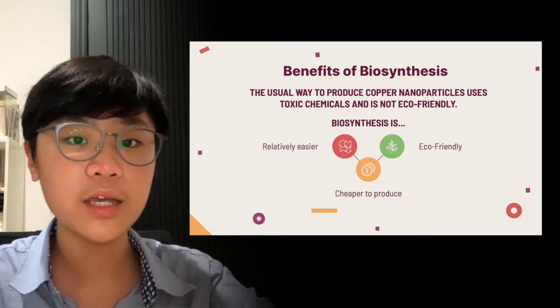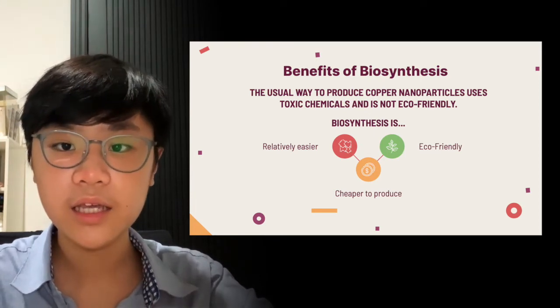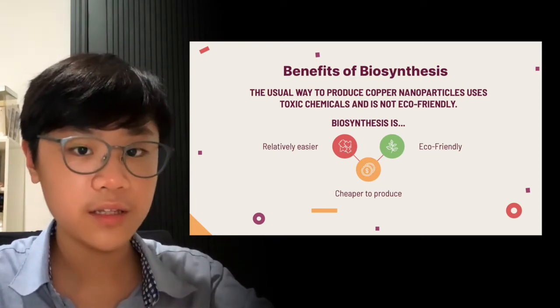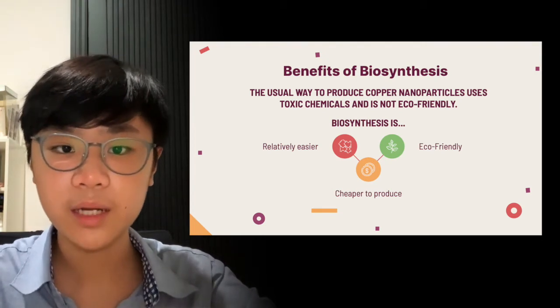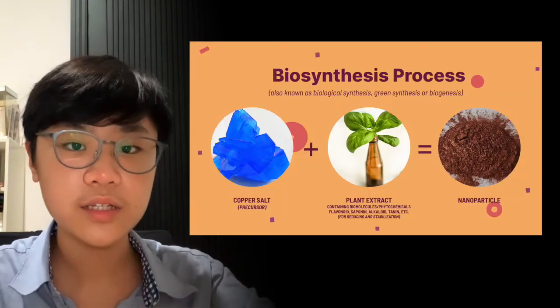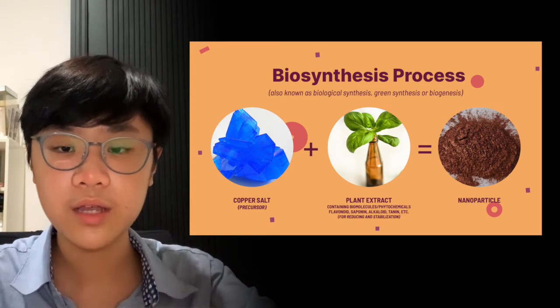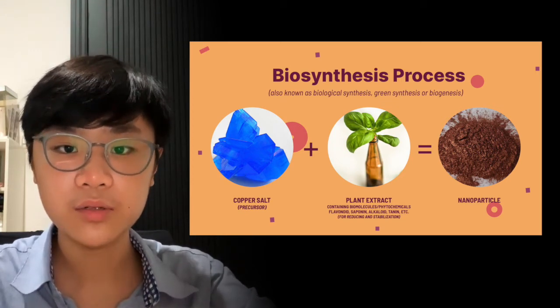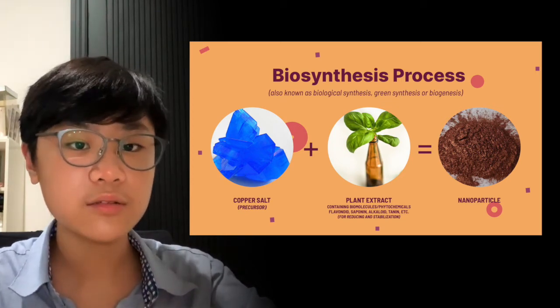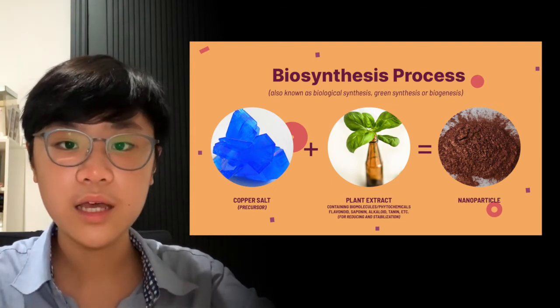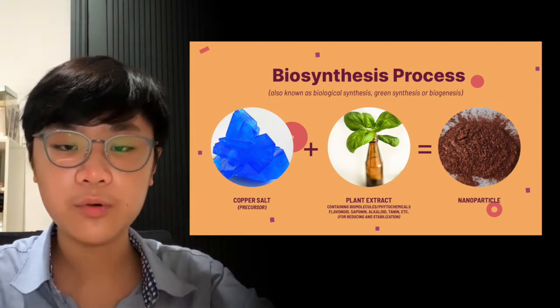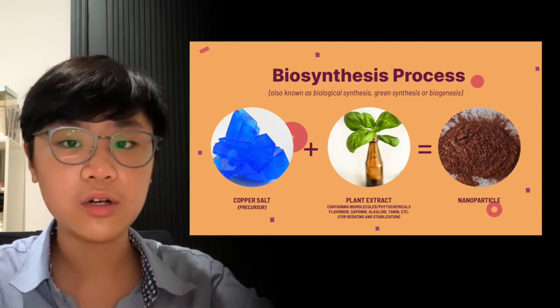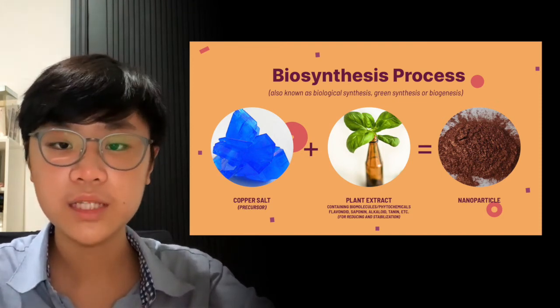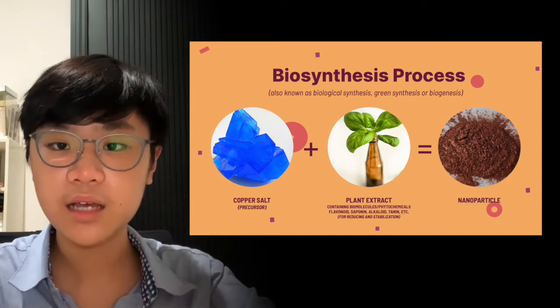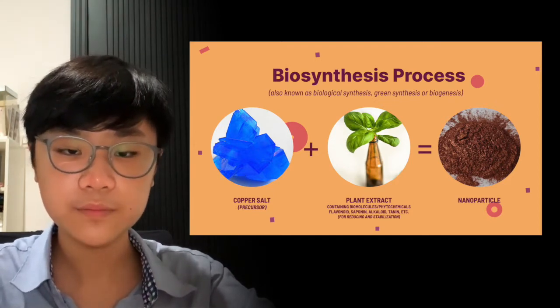This is where the biosynthesis process comes in. It is relatively easier, eco-friendly, and cheaper than conventional chemical processes. Essentially, the copper salt precursor mixes with plant extract to produce the nanoparticle, from big crystals to small nanoparticles. The plant extract contains chemicals that break down the bigger copper salts into the copper nanoparticle. These chemicals are called biomolecules or phytochemicals, like flavonoids, saponins, alkaloids, and tannins.